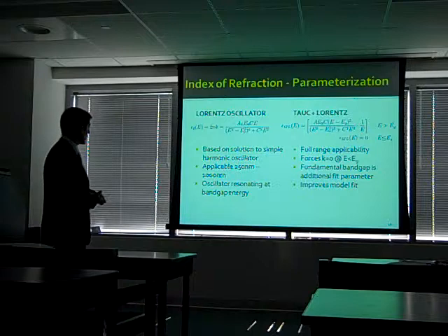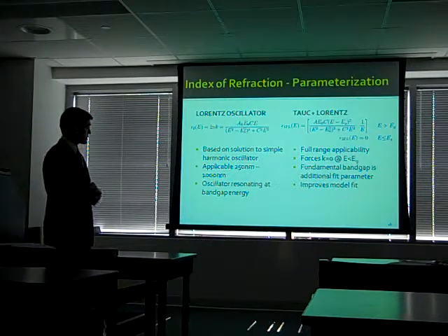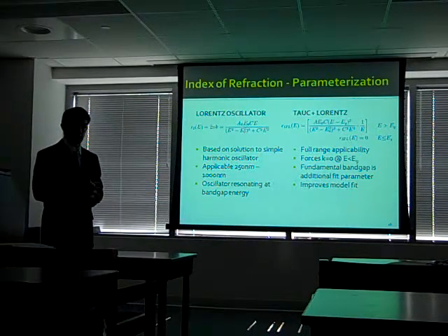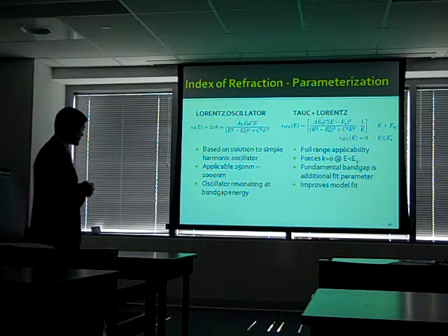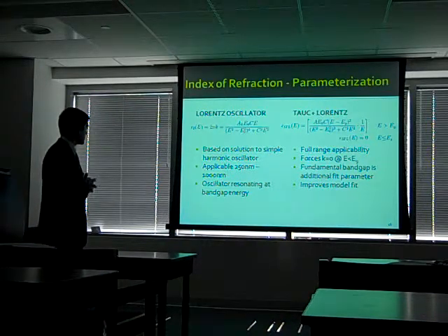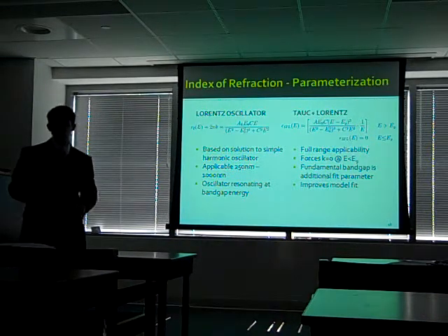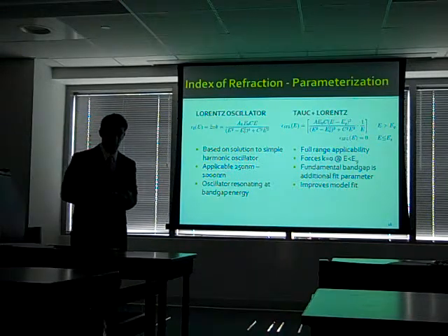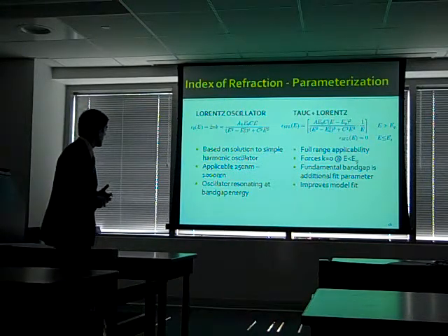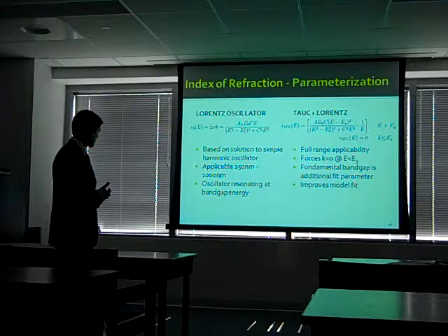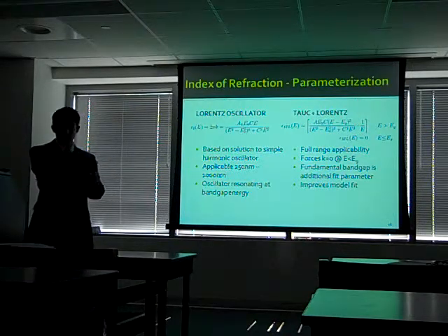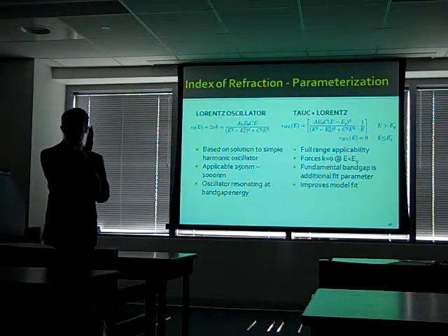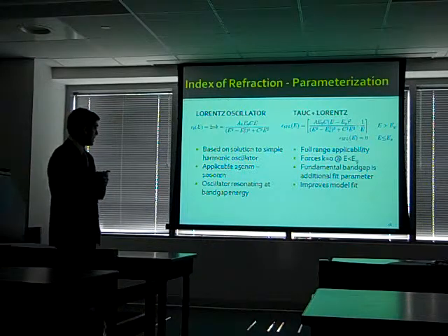So we use parametrizations to model the optical constants of these films. One common one that is used is the Lorentz oscillator. It's based on the solution to the differential equation of a simple harmonic oscillator. There are 3 fitting parameters: the amplitude of the oscillator, the center energy of the oscillator, which is where it's located, and the broadening term, C.